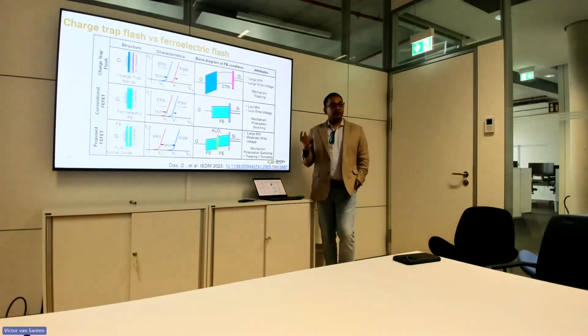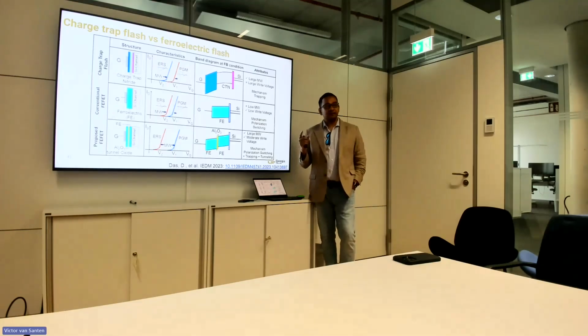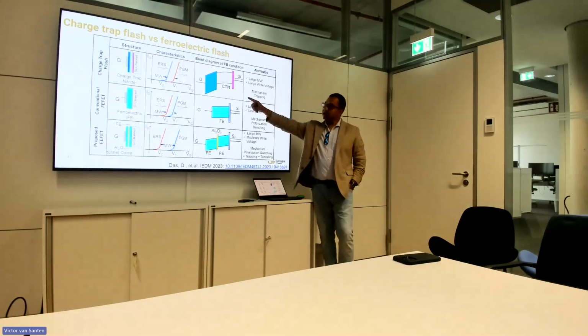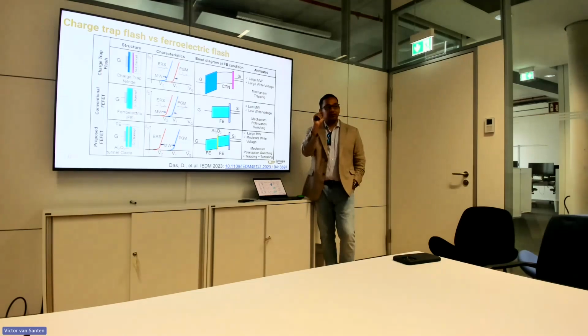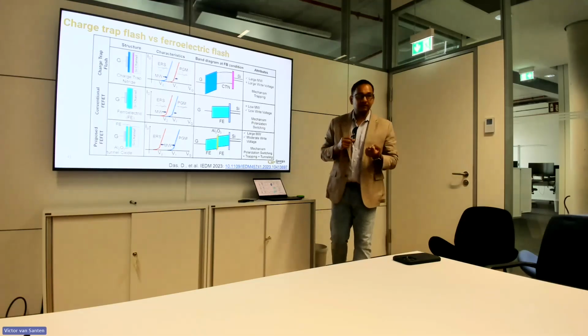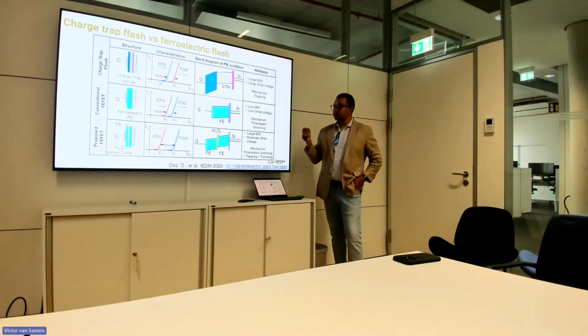We don't have the experimental result yet to prove or disprove that. But the main thing is that in the case of NAND flash, the trapped charges are trapped within a bulk. Here, the trapped charges are at the interface, so the amount of space that they have to move is much smaller, and also they're bound by the polarization. So we think that there will be lateral charge migration effects in what we call the band engineered ferroelectric field effect transistor. There will be lateral charge migration, but to a much lesser extent than in flash because those trapped charges are truly at the interface.